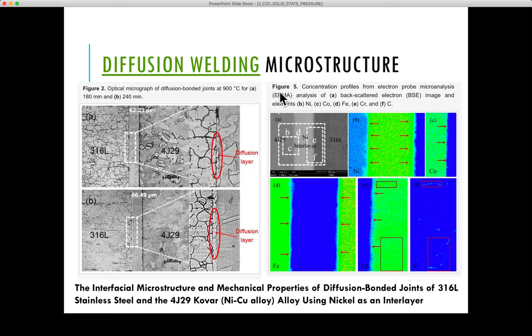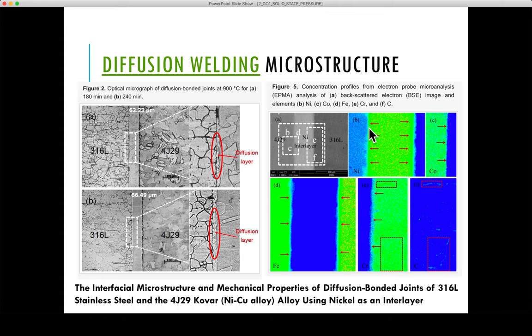In Figure 5, EPMA (electron probe micro analysis) of this weld is shown. Figure A is a scanning electron microscope image, and B, C, D, E, and F are individual element EPMA analyses. Figure B shows that nickel has diffused into the steel — the color variation and transition between blue and green indicates diffusion. Once the diffusion occurs, a joint is essentially created.